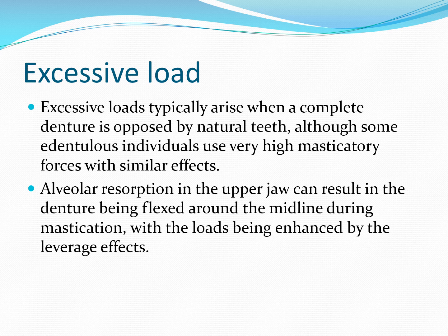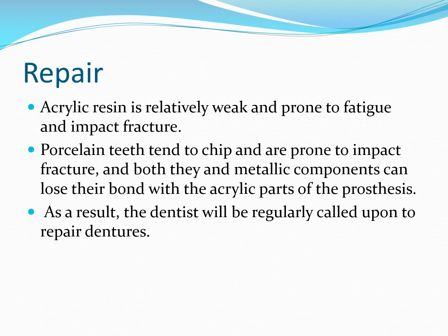Alveolar resorption in the upper jaw can result in the denture being flexed around the midline during mastication, with the loads being enhanced by the leverage effect. So this will create a leverage effect, and the denture will fracture from the center. Acrylic resin is relatively weak and prone to fatigue and impact fracture. Porcelain teeth tend to chip and are prone to impact fracture.